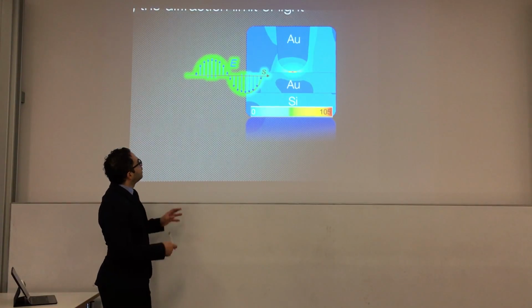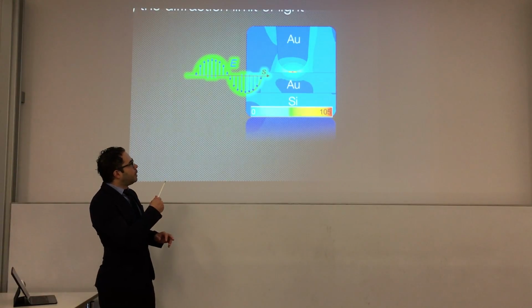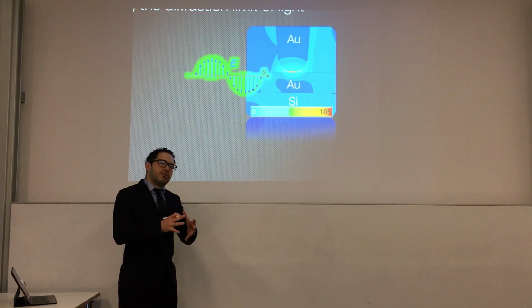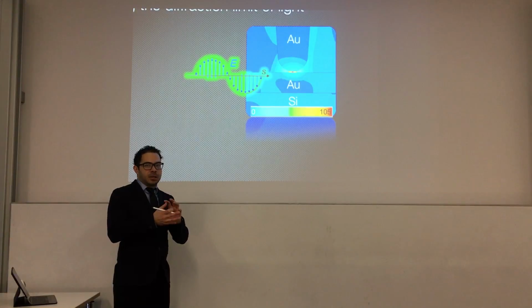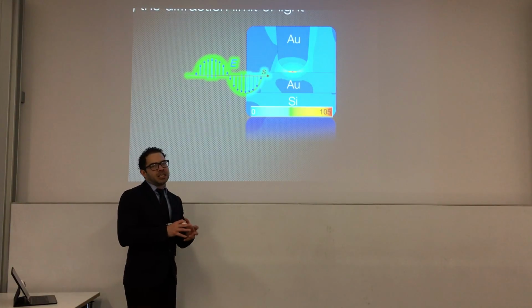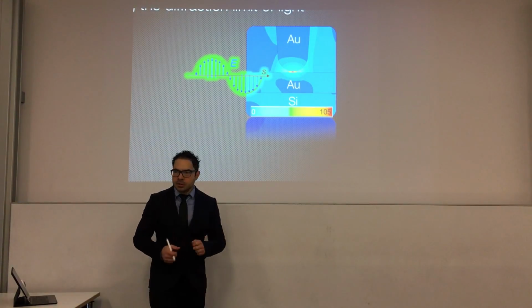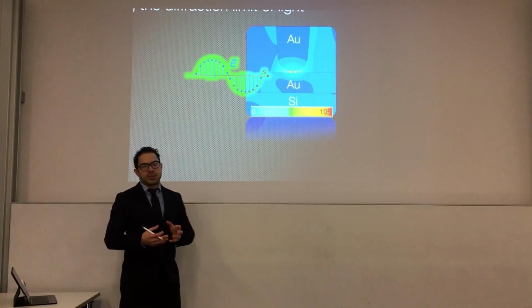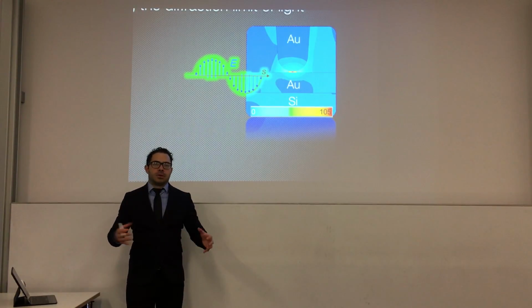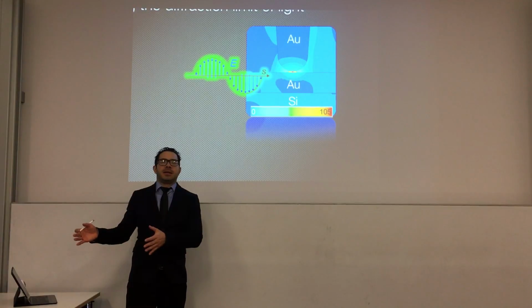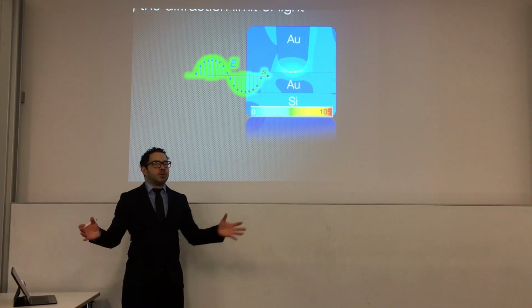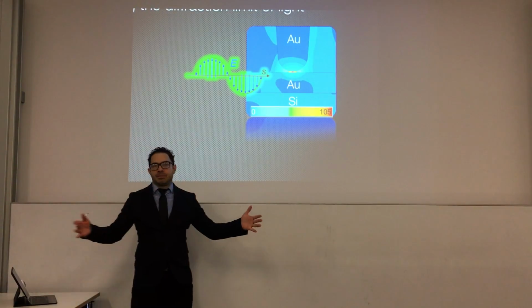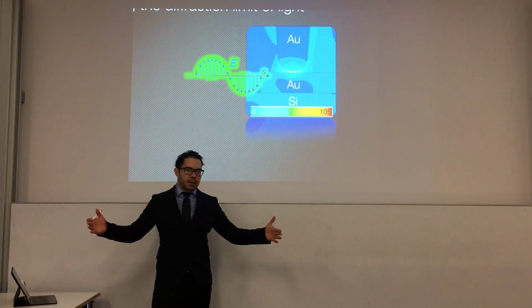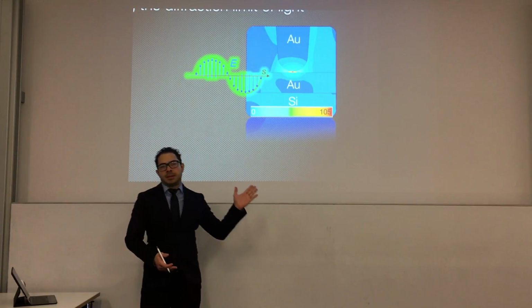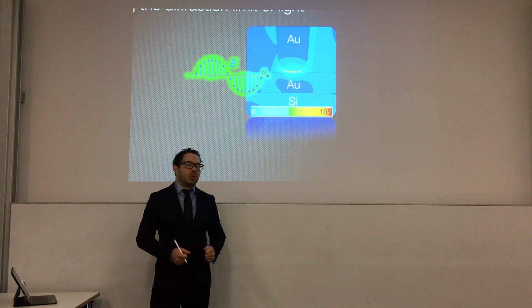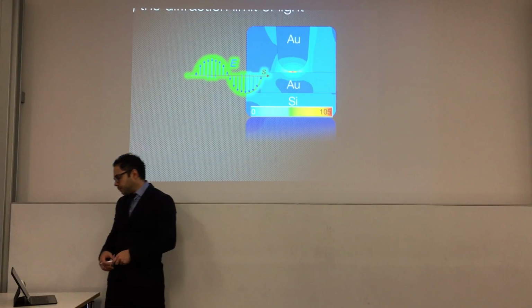So if you see this 10 nanometers tip, you have a localization of this highly confined light in a location much smaller than 10 nanometers. So this confinement acts also as a localized light source. Suddenly you're not limited anymore by the diffraction limit of light, which imposes for similar wavelengths a spot size of 250 nanometers. Here you have a spot light source that is smaller than 10 nanometers.